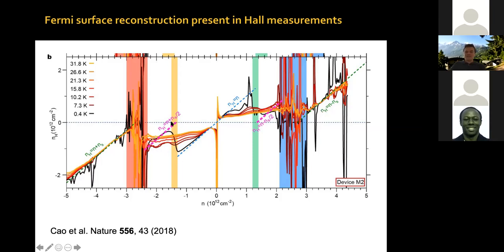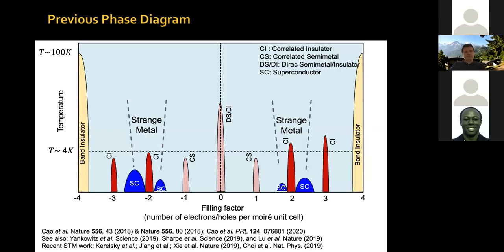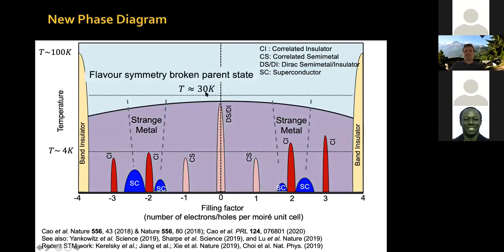Okay, and that reset, that Fermi surface reconstruction, now we understand it as this phase transition from filling these 4 flavors with an ever increasing Fermi surface to then having a reset back to charge neutrality once this Dirac revival happens. Okay, so these experiments have shown a lot of understanding of some of our initial puzzles in our initial discovery. So in this phase diagram, now we have to add a region of high temperature, certainly up to about 30 Kelvin. Now recent data seems to suggest that we have even this region of flavor symmetry broken parent state after each correlated insulator state, at all temperatures below which this interesting correlated physics occurs.